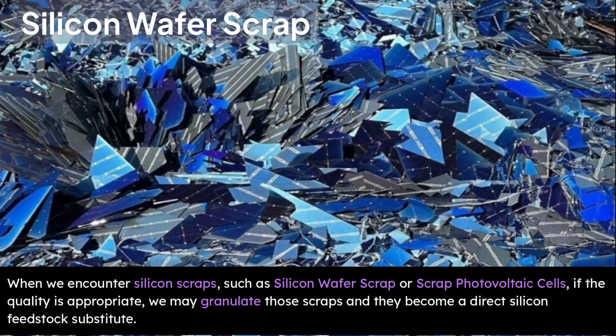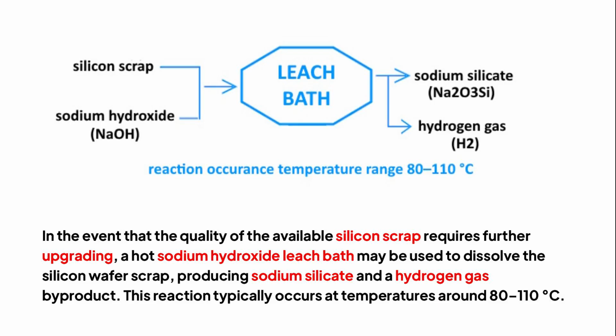When we encounter silicon scraps, such as silicon wafer scrap or scrap photovoltaic cells, if the quality is appropriate, we may granulate those scraps and they become a direct silicon feedstock substitute. In the event that the quality of the available silicon scrap requires further upgrading, a hot sodium hydroxide leach bath may be used to dissolve the silicon wafer scrap, producing sodium silicate and a hydrogen gas byproduct. This reaction typically occurs at temperatures around 80 to 110 degrees Celsius.